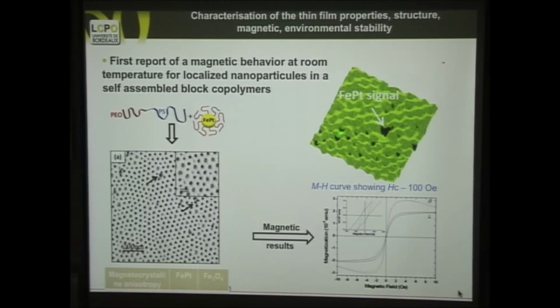So what we discover here is that we see some of them, not all of them, the 20%. But that doesn't mean that they are not there, because if the magnetization is horizontal with respect to the surface, then the MFM will not see it. However, if it's vertical, we'll see it. And that's something that we have to work on.